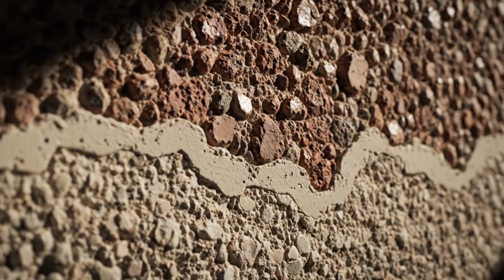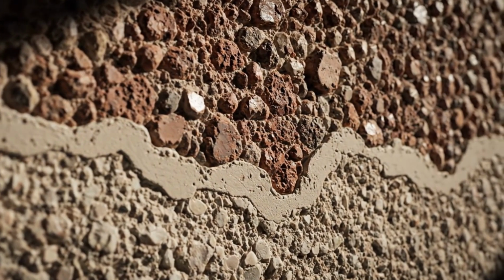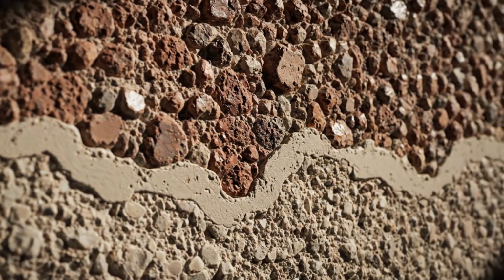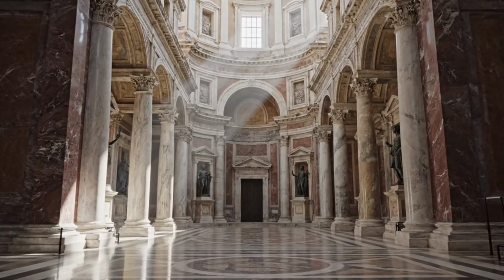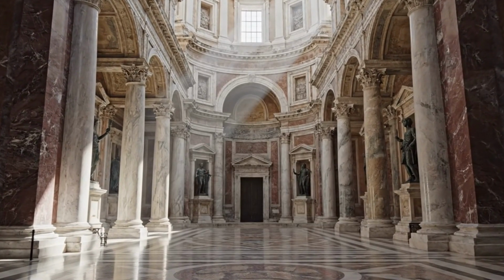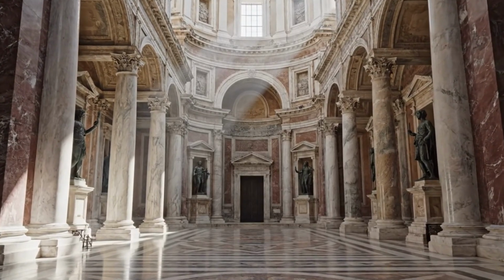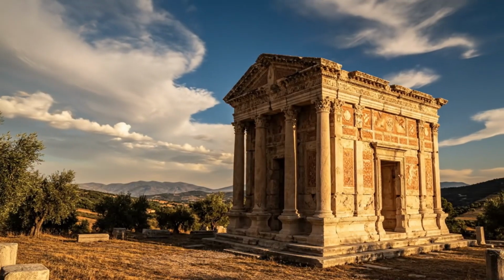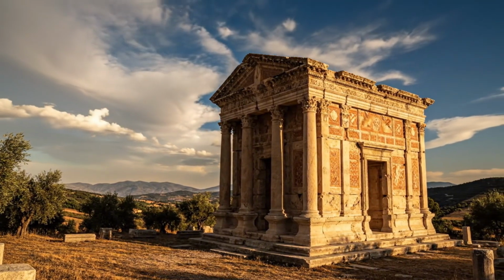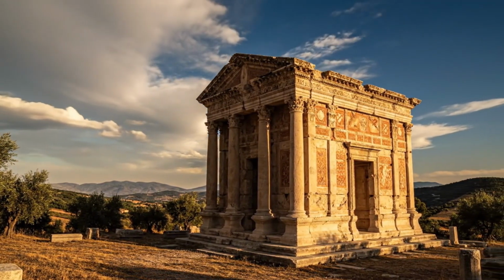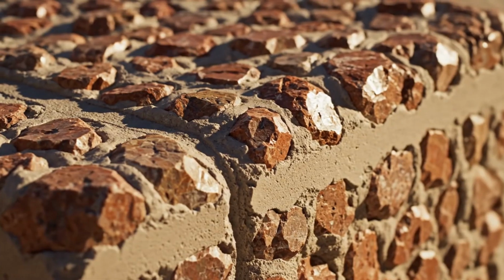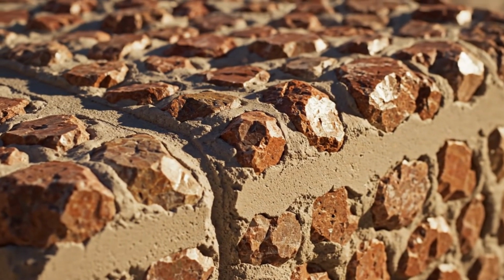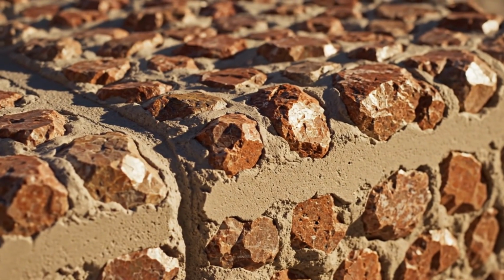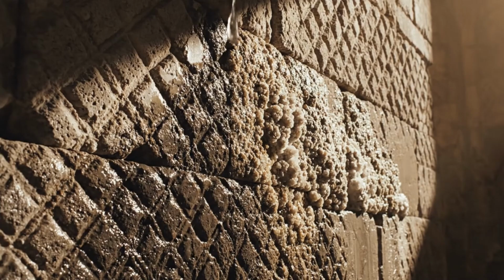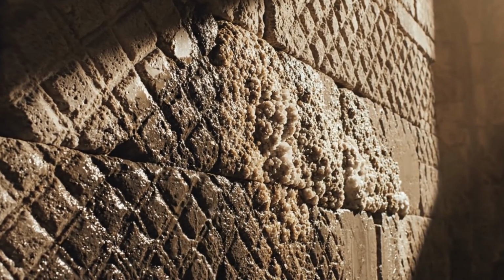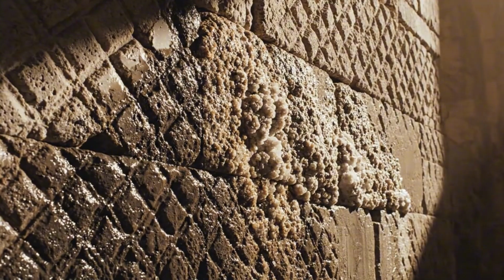The findings from the investigation of lime clasts reinforce this interpretation. When microcracks develop and intersect reactive lime inclusions, the resulting calcium-rich solutions can precipitate as calcium carbonate within the fissures. This process effectively restores continuity across damaged interfaces. The interfacial zones are not passive boundaries. They are active regions capable of responding to environmental change. Water, which often accelerates decay in modern systems, becomes a participant in strengthening the Roman material.